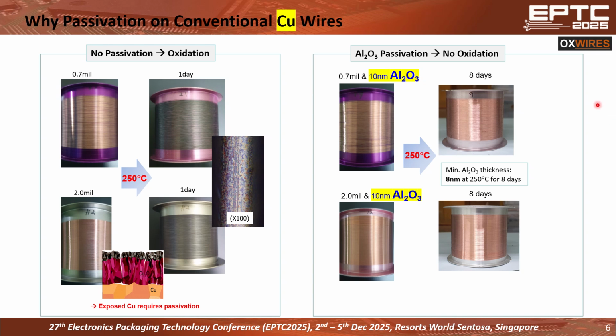We can also apply the passivation coating on the surfaces of a conventional copper wire as well. On your left-hand side, no passivation is applied to the copper wire at very high temperature, like 250 degrees C. At the end of one day, you're going to get very serious copper oxidation, very serious color change. But on the other hand, after we apply the Al2O3 passivation on the surface of the copper wire at very high temperature, even after 8 days, there's no color change, indicating that this Al2O3 passivation protected the surfaces of the copper wire from oxidation.